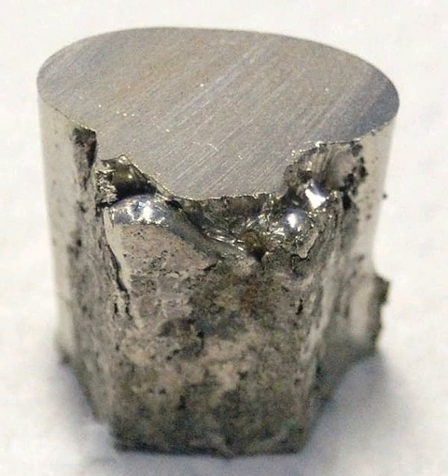Nickel is obtained from nickel carbonyl by one of two processes. It may be passed through a large chamber at high temperatures in which tens of thousands of nickel spheres, called pellets, are constantly stirred. The carbonyl decomposes and deposits pure nickel onto the nickel spheres. In the alternate process, nickel carbonyl is decomposed in a smaller chamber at 230 degrees Celsius to create a fine nickel powder. The byproduct carbon monoxide is recirculated and reused. The highly pure nickel product is known as carbonyl nickel.